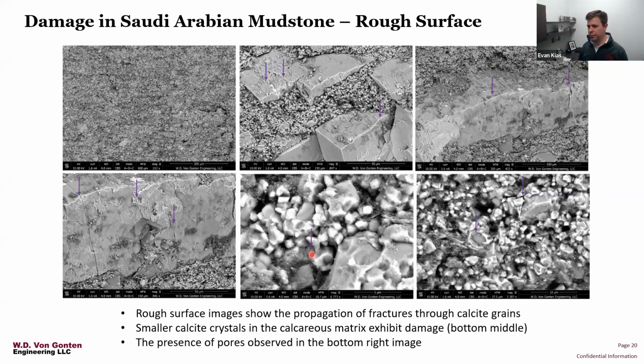Yet the amount of volume strain we were seeing during these tests was on the order of 3 to 4%. It seemed that some fractures propagating might not fully explain it.